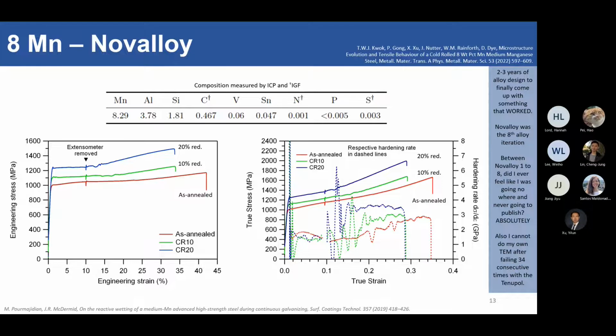So we cold rolled our steels to about 10 and 20% reduction. I'm going to call these CR10 and CR20 from now on. As expected, when you cold roll the steel, the strength goes up, right? It gets stronger. What's interesting is that we have this introduction of this very flat bit, this stress plateau called the yield point elongation. But what's more interesting to me actually is this bit here where the strain hardening rate goes up. So this bit where it kicks up higher.